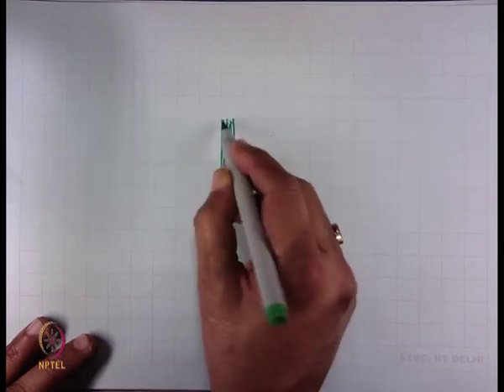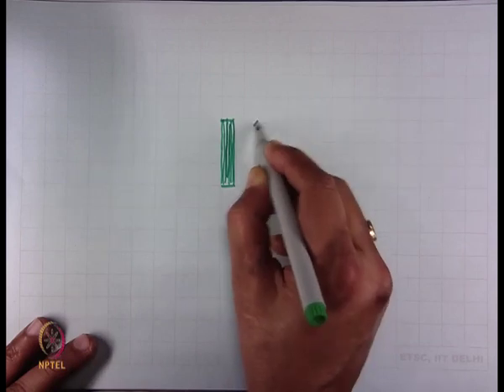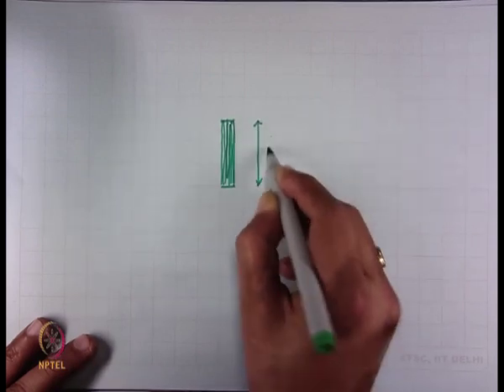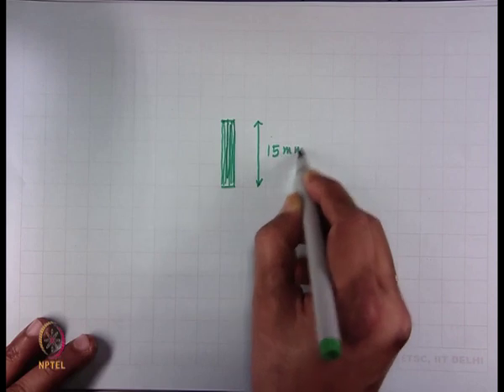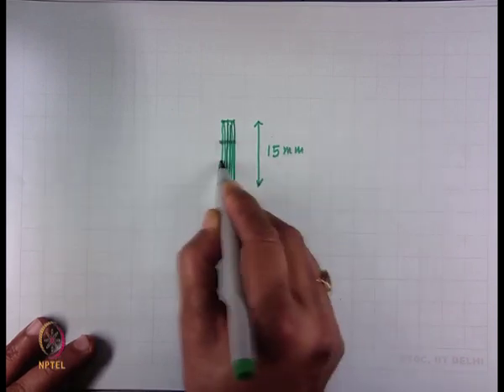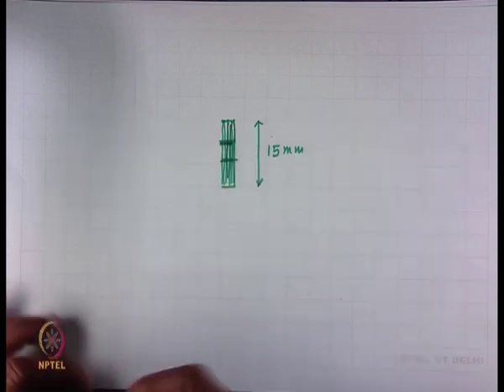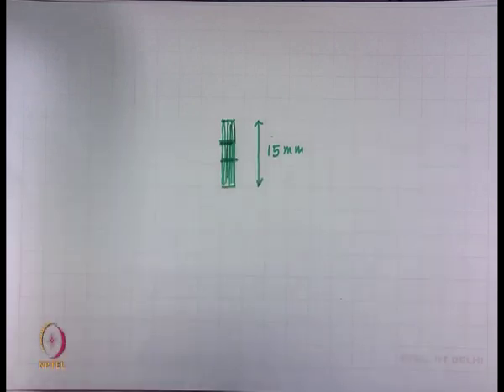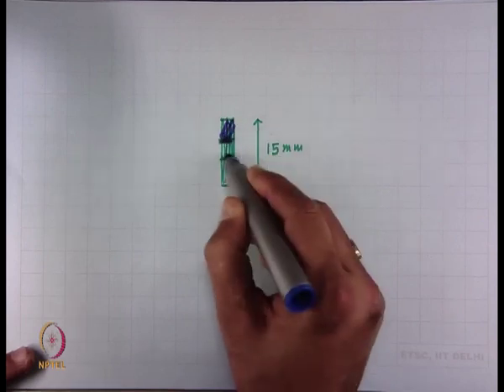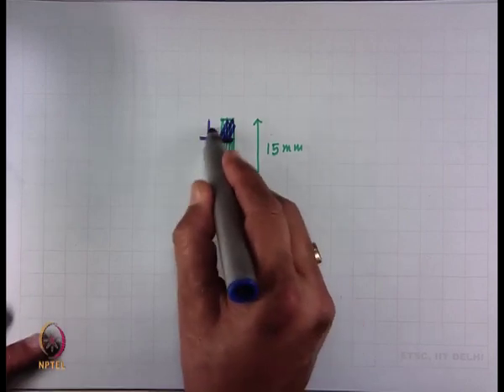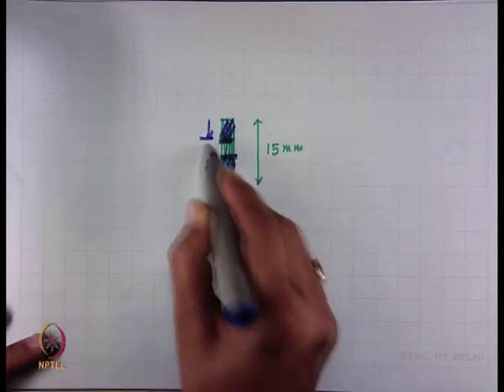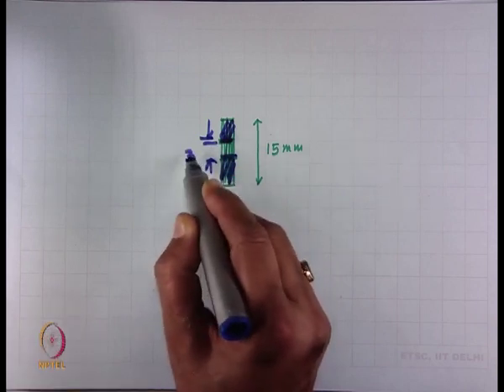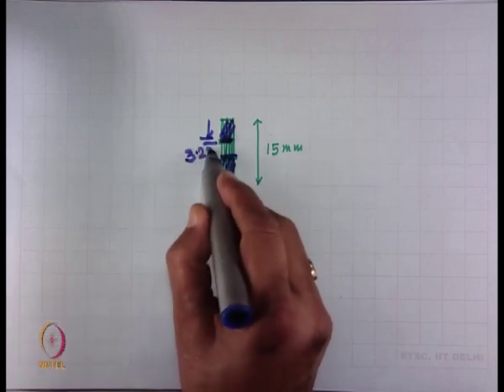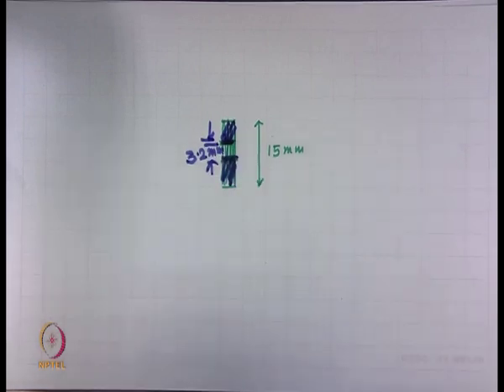This is the fiber bundle. This length is 15 millimeter, and once we are gripping, these are the grips. This is the jaw, and here it is a jaw, and this length, this is gauge length, which is 3.2 millimeter. So, bundle strength test is done in this fashion.